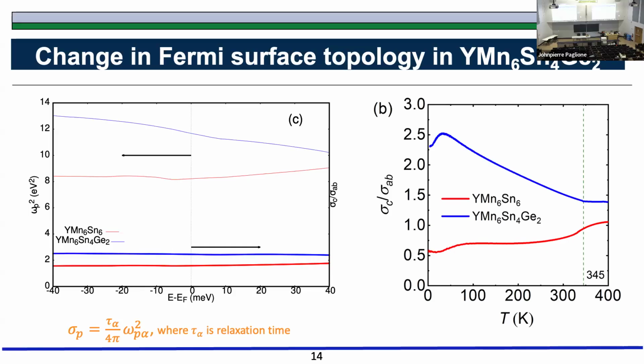These calculations were done at zero temperature, right? So at low temperature, you can see the same behavior. So basically, by putting germanium, you brought a small change in the magnetic structure. That magnetic structure led to a change in Fermi surface that you can measure with a basic resistivity measurement. That was one of the stories.